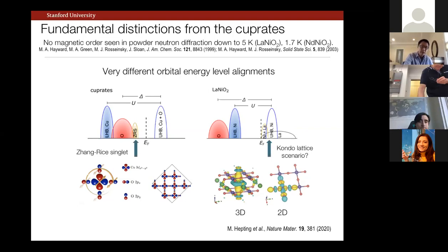Okay. And so early on, this led various people, in my own discussions, Jan Zaanen was the first to point this out. He was on sabbatical last year at Stanford, saying this is rather interesting in that it might be an oxidic analogy to a Kondo system, meaning rather than a narrow 4f band in the midst of other things, here we have this rather narrow upper Hubbard band in the midst of these 5d states. But whatever else is true, what we also can say is that if we are thinking about doping in this system, let's say a little bit of hole doping, we're really then talking about states derived from these nickel 3d and in this case lanthanum 5d states.